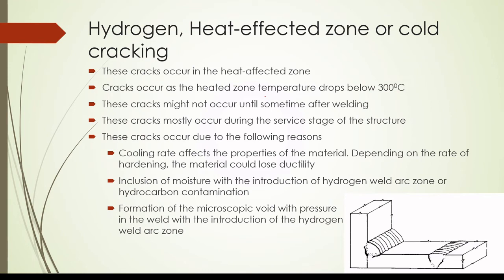The next issue is hydrogen heat affected zone or cold cracking. Cold cracking occurs in the heat affected zone — the zone between the weld and the base metal. Cracks occur as the heat affected zone temperature drops below 300 degrees Celsius. These cracks might not occur immediately after welding; mostly these cracks occur in the service stage of the structure, or even after some time after welding.